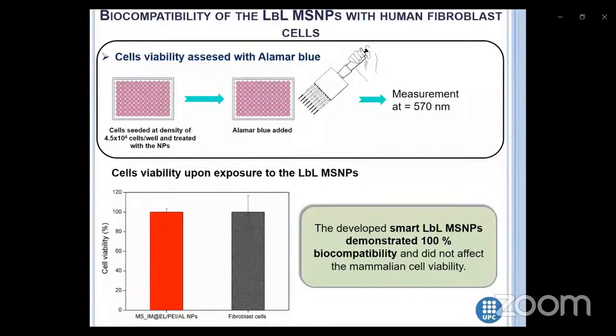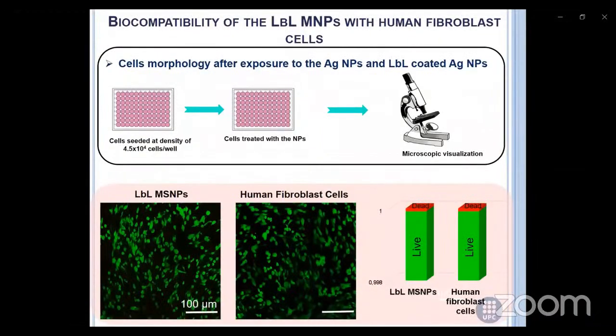So it was also important to study the toxicity of these nanoparticles. The nanoparticles didn't affect the fibroblast cell viability and demonstrated 100% biocompatibility. The microscopic observation after fibroblast human cells exposure to the layer-by-layer nanoparticles showed that the nanoparticles didn't affect the cell morphology.